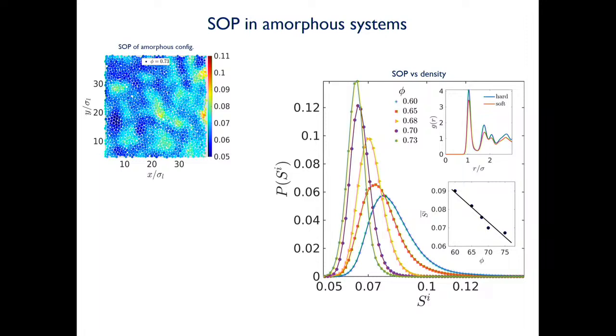It's an averaged plot for all these particles. You look at g(r) for the particles that have larger structure order parameter, the soft particles, and then the particles that are hard. You can see that hard particles are associated with a more structured environment. This confirms our intuitive understanding of disordered systems. There are certain regions where the packing is loose and certain regions where the particles are tightly packed. In the tightly packed regions the system should be hard, and where the particles are loosely packed, it should be associated with higher softness. That's what it confirms.